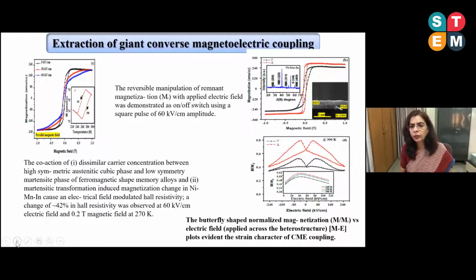We were also able to see the butterfly loop of normalized magnetization versus electric field, which is evidence of the strain character of the CME coupling. The coupling could be strain mediated, charge mediated, or both. We observed, as in the literature, that whenever this butterfly curve appears, it is significant evidence that the coupling is strain mediated.